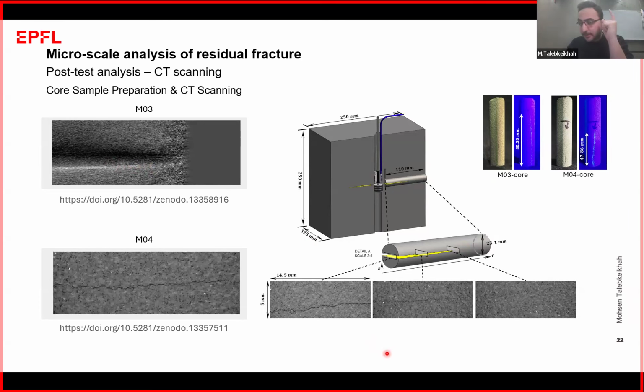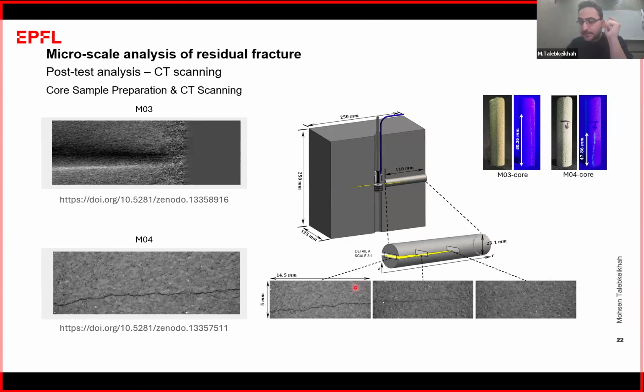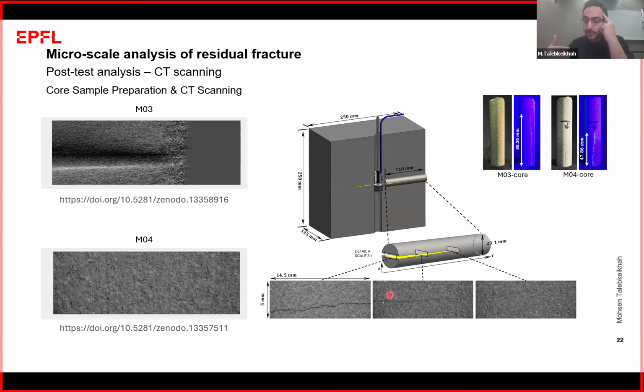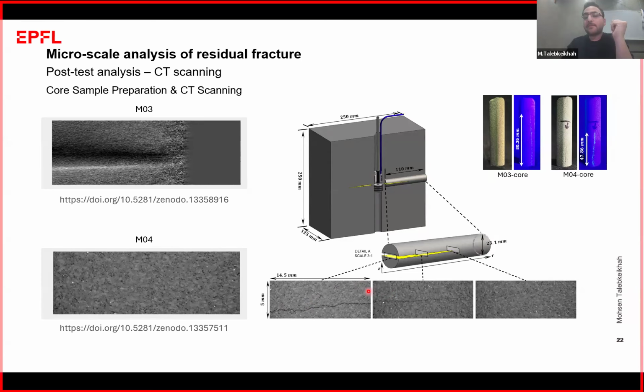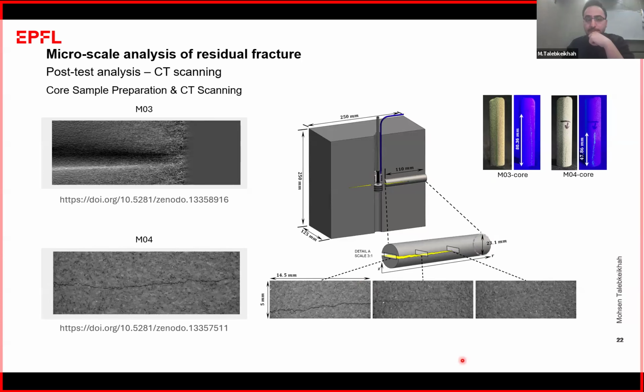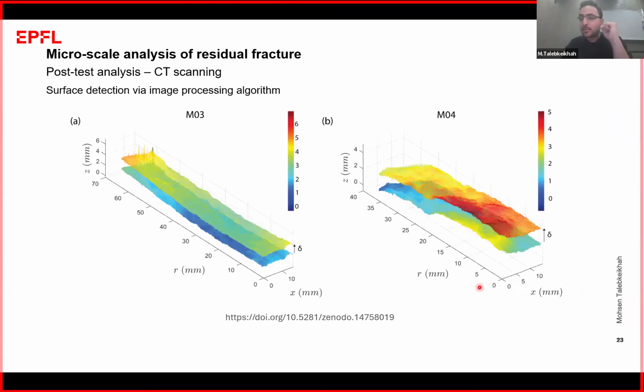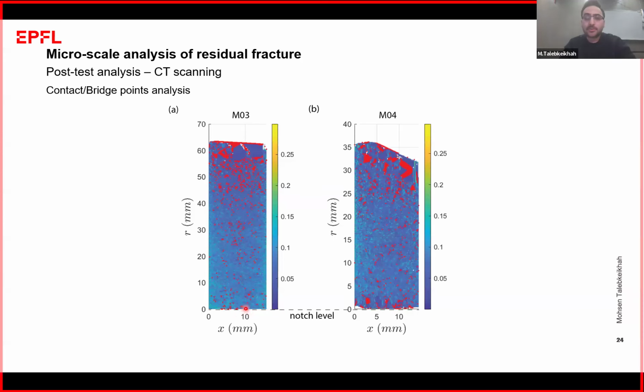So by knowing the size of each pixel in this image, which is 10 micron, known from our CT scanning, we can reconstruct both the upper and lower fracture surfaces for both experiments. And by subtracting these 2 surfaces from each other and applying a specific threshold, we arrive at some red points along our fracture surface. These red points are the points related to the contact and bridge points along the fracture surfaces.